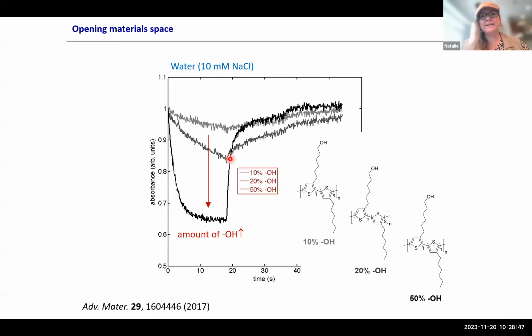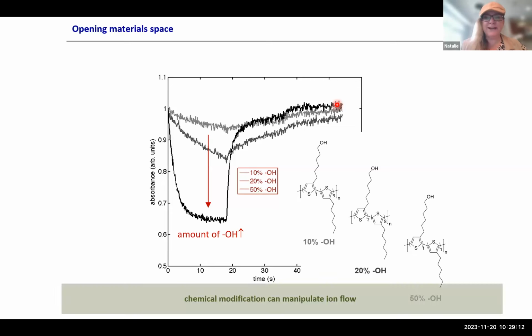And what you see is the more alcohol groups, possibly not very surprisingly, you have in your system, the more ions you can absorb, and therefore you have more rapid oxidation. You see, you can get them out, but you have to go to a bit of a higher bias to really get all the ions out. So chemical modification can manipulate ion flow. Again, not surprising, Natalie, but using, yes?